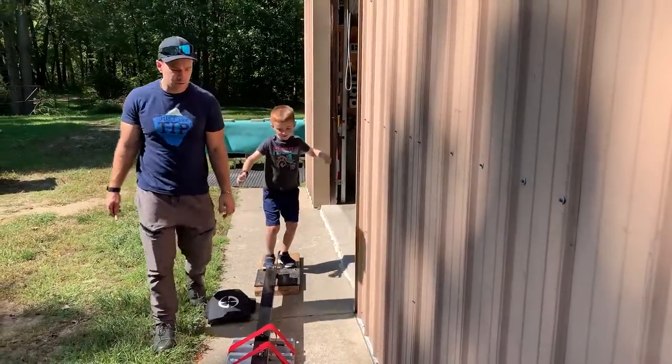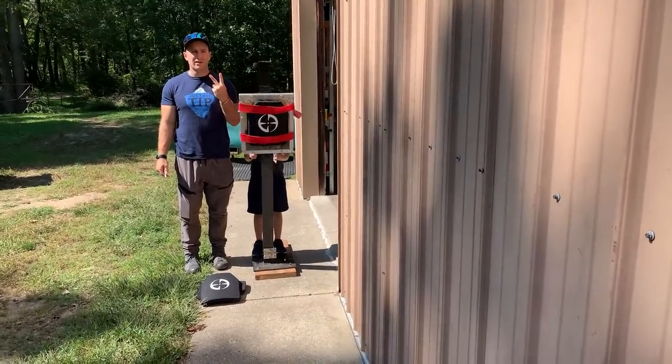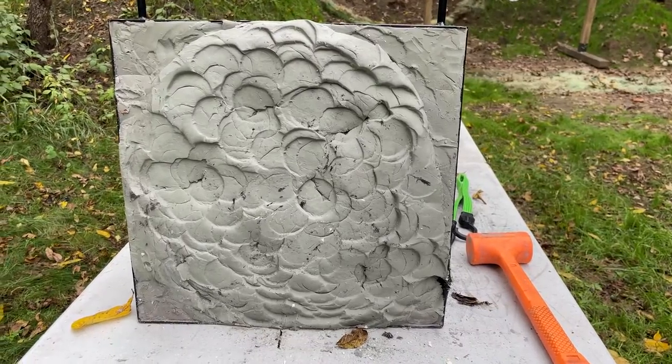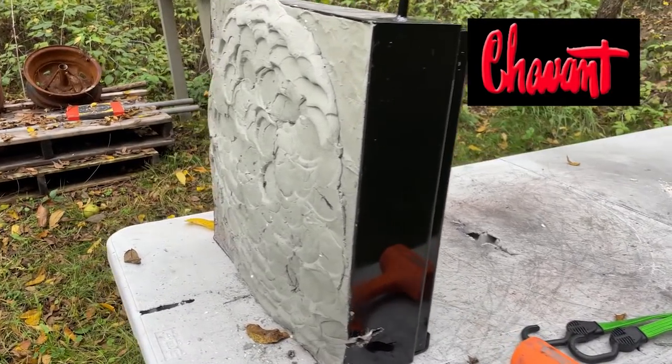Since this is a ceramic plate, we've gone ahead and dropped it on its face two times per the NIJ standard. I also use a giant clay briefcase filled with Roma Plastilina Number 1 clay donated by Chavant. We have two barrel lengths for this test: a 20-inch and a 29-inch.